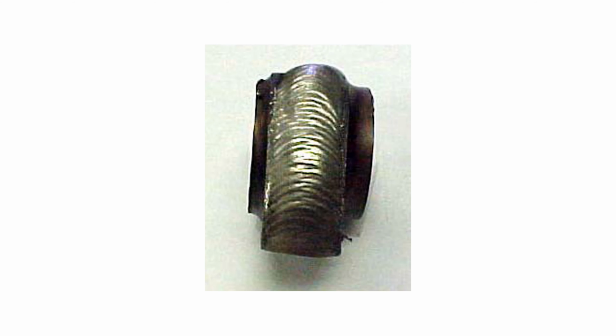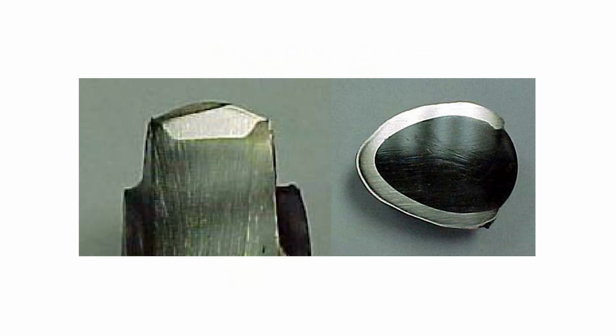One of the challenges of welding these NASCAR cams was the fact that they had already carburized these shafts before they gave them to us to weld. And the edges of the weld are only about 40 thousandths thick, very easy to melt. So that's when we developed synchronized pulsing. And on the camshafts, we actually reduced current at the edges to avoid melting those sides. In the video that you're going to see today, we flipped this backwards and we're increasing the current on the edge to ensure good sidewall fusion.